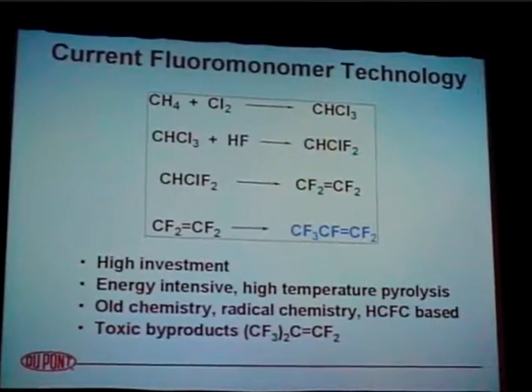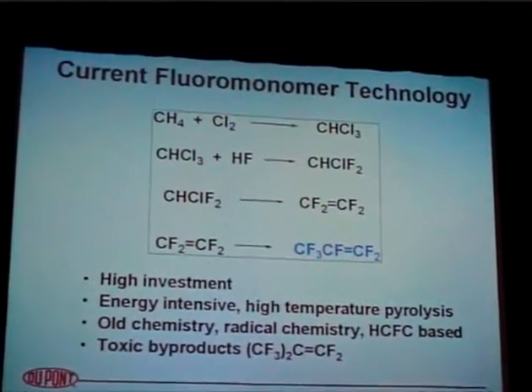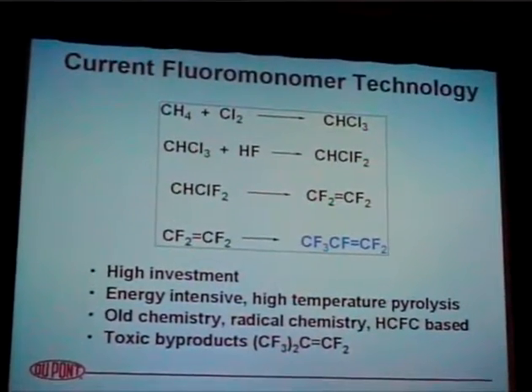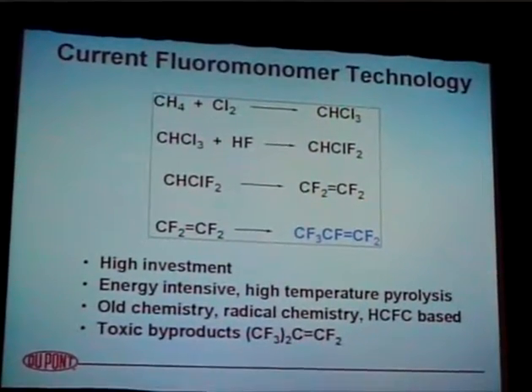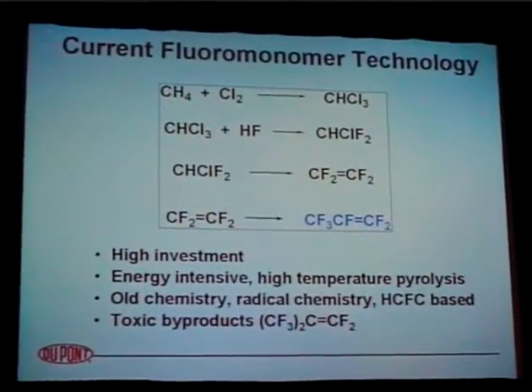Today, the process is run as it has been run for maybe 40 years. It's a thermal reaction starting with methane, chlorine, and chloroform. Chloroform is reacted with HF to give difluorochloromethane, HCFC-22, which is then heated up at about 500 degrees centigrade to pyrolyze it. That gives you difluorocarbene radicals, which then combine together to make tetrafluoroethylene.